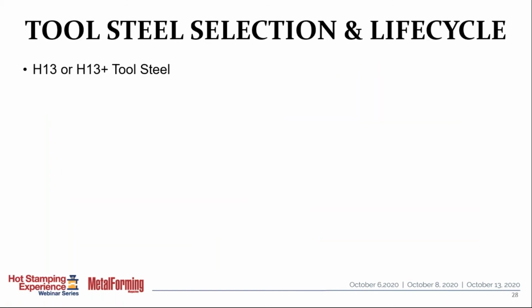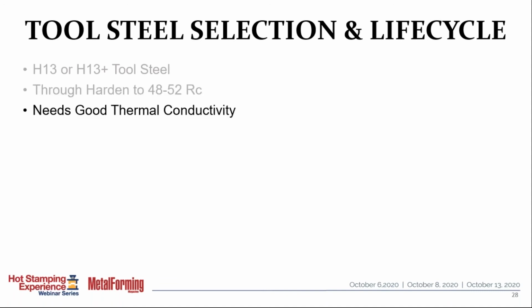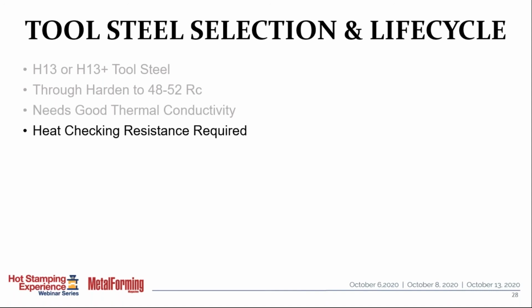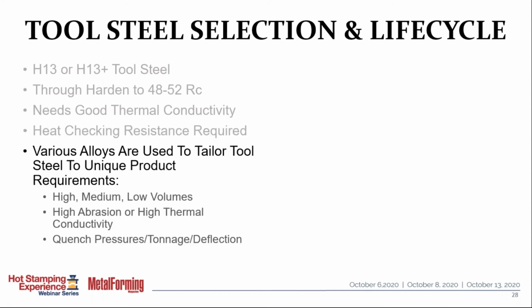So when we select tool steels, we generally are using an H13 tool steel. It's through hardened. We need good thermal conductivity in the material to take the heat out of it and put it into the water. The tool's going to get hot and cold and hot and cold, and so there's going to be a need for heat checking resistance. So there's a lot of different alloys available that you can choose from in order to tailor the tool steel to the requirement of the project.